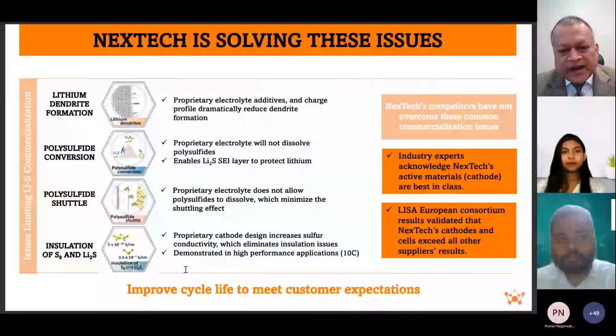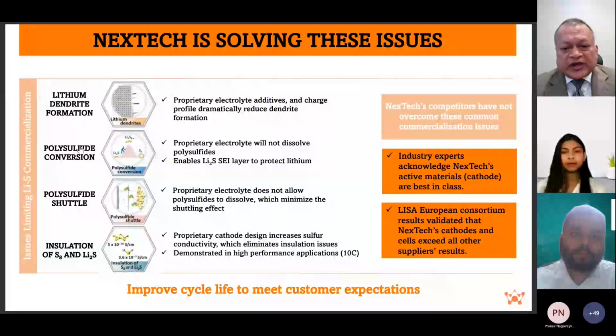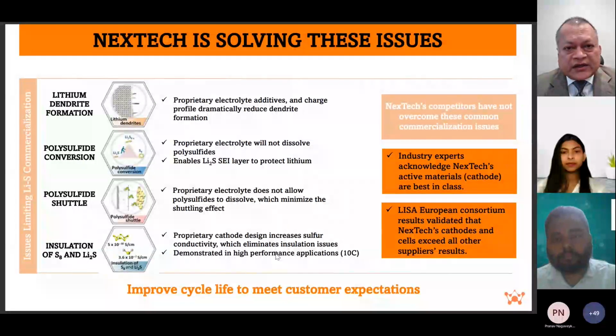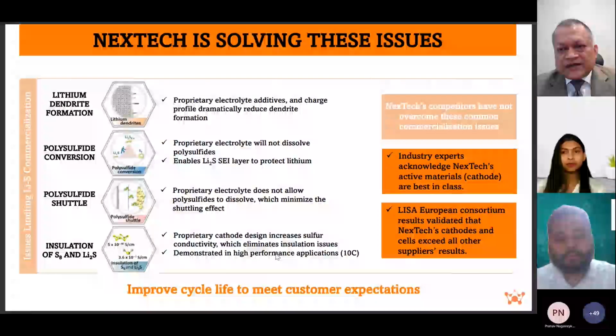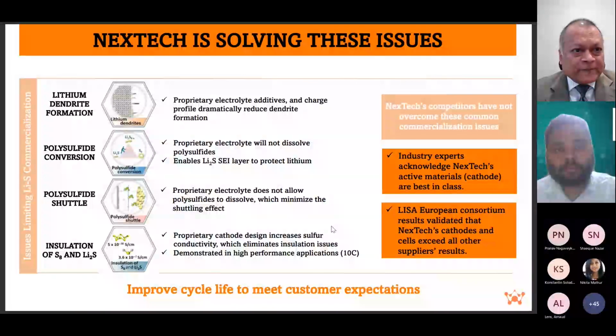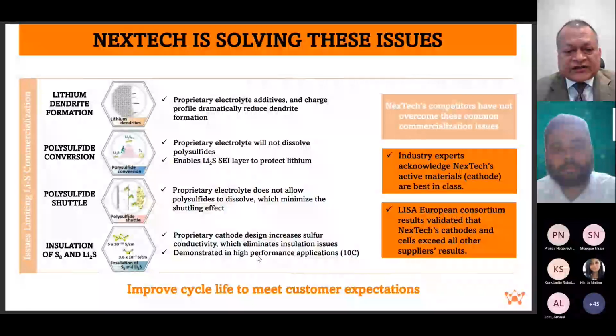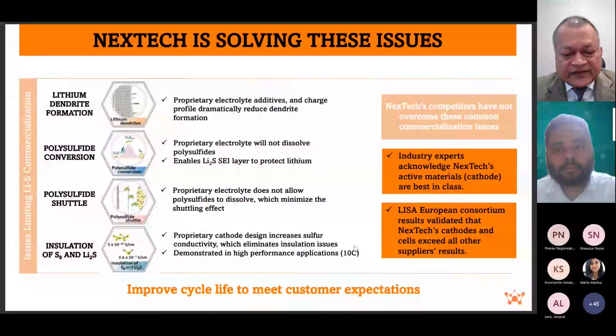We have tested our batteries up to 10C. You can continuously discharge them or recharge them at 3C, no issues. And you can discharge the batteries at 10C for up to 1 minute. And this is what you need, especially in an application like a two-wheeler, where the initial acceleration is a definite requirement. The 10C capability helps you quite a bit. Next slide, please.